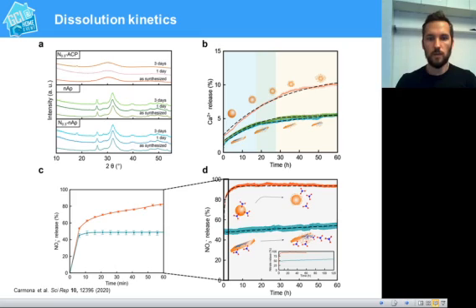Interestingly, if we look at nitrate release, we can see that the nitrate incorporated in the amorphous material is much higher in quantity, but the release is much faster, as you can see in figure D. And this is interpreted as weakly bound nitrate molecules at the surface of the particles, whereas a completely different behavior is obtained for the nanoplates.